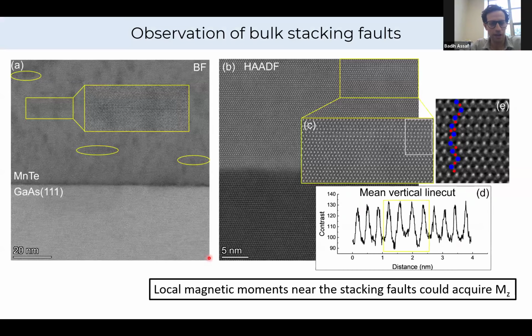What we also find is that MnTe grown on gallium arsenide has a very peculiar type of defect. In TEM, there were regions where we find that the periodicity of the lattice is interrupted. There's a zoom in on these shown here, where you can see that this zigzag or tilted pattern appears down here in the pristine region, and then all of a sudden there's a layer that appears a little bit more stacked vertically. The two tellurium atoms are stacked vertically on top of each other right here. If you zoom in and study this carefully, it turns out that there's a stacking fault along these layers, and there's a missing tellurium atom. You can see that right here, where there are two red dots corresponding to manganese right next to each other.